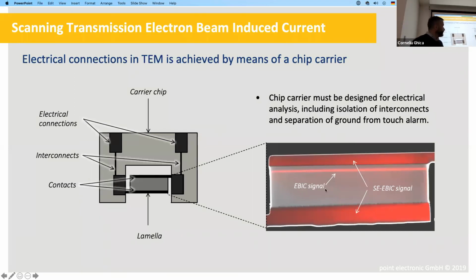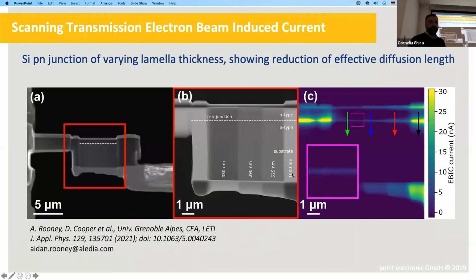But we also see an additional signal that comes from inside the silicon lamella. So then that's the junction, the one that we're aiming for. As an example of working through how this works, this is a known sample. Typically we work with nano samples, but this is a known test sample, just to figure out that everything works and what information we can extract.